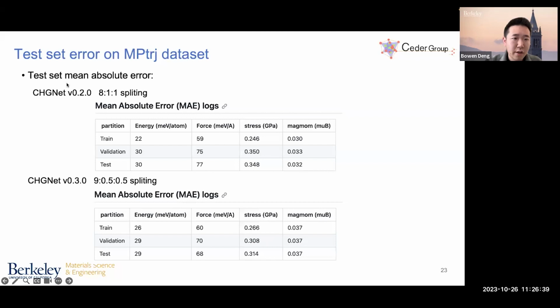So here are the test set mean absolute errors. On the top is CHGNet 0.2.0, where we use the 8:1:1 splitting. At the end, we achieved 30 meV per atom, 77 meV per angstrom, 0.348 GPa for stress, and 0.032 μB for magmom. This is the version we published with the paper. We just released another version, CHGNet 0.3.0, which we trained with a 90:5:5 splitting, and we achieved slightly better results, especially on the test set and validation set.